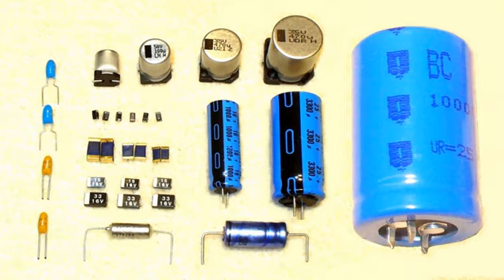Applying a positive voltage to a wet capacitor causes a reforming self-healing process which repairs all weakened dielectric layers, and the leakage current remains at a low level. Although the leakage current of non-solid ECAPs is higher than current flow over insulation resistance in ceramic or film capacitors, the self-discharge of modern non-solid electrolytic capacitors with organic electrolytes takes several weeks.